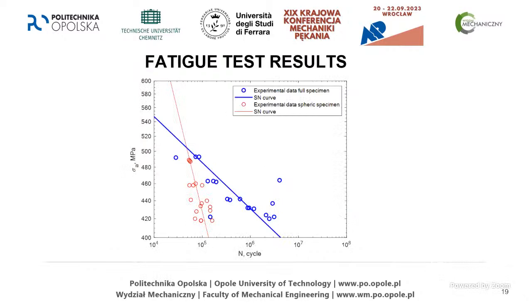If we put them together on one diagram, you can see they look like this. The levels in terms of the tests have been chosen to be the same. After we had the scans, we have measured the diameters of the voids for every specimen, and we have calculated what should be the bending moment in order to obtain the same stress levels as for the full specimens. As you can see, we have obtained results like this. So we can notice that the powder doesn't improve the fatigue capabilities in terms of normal full printed specimens, as was also expected.